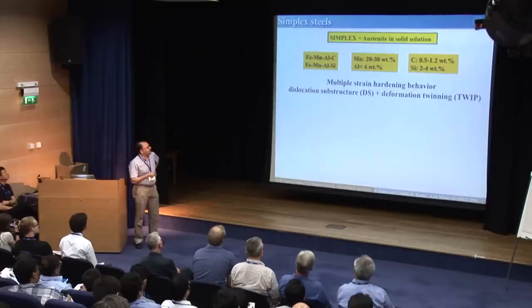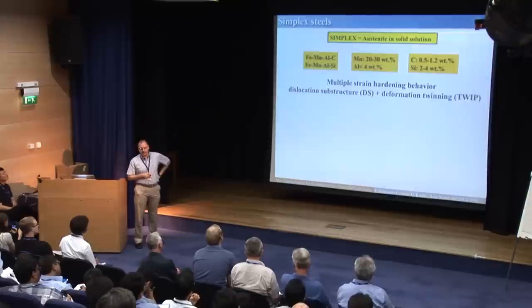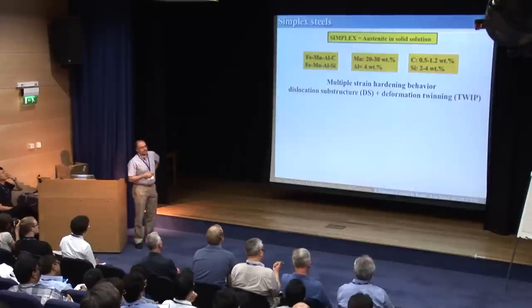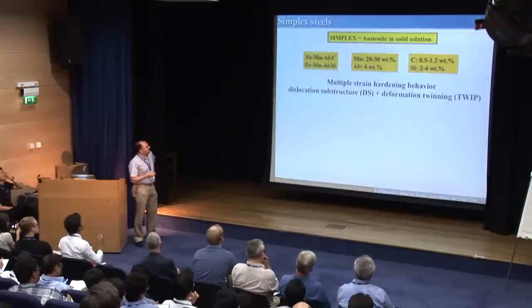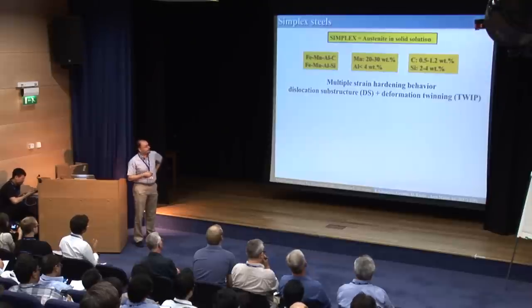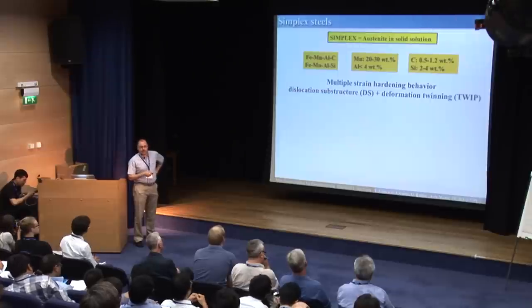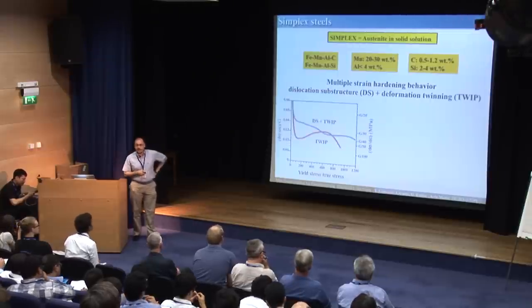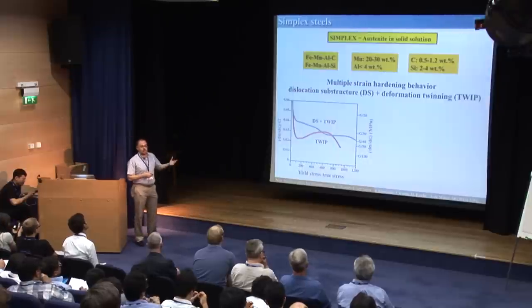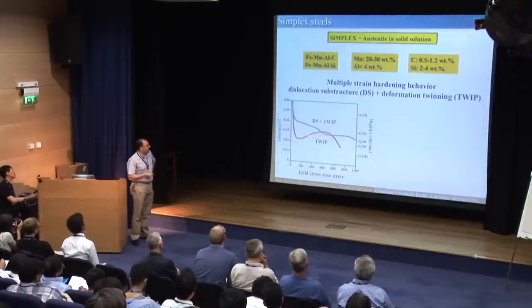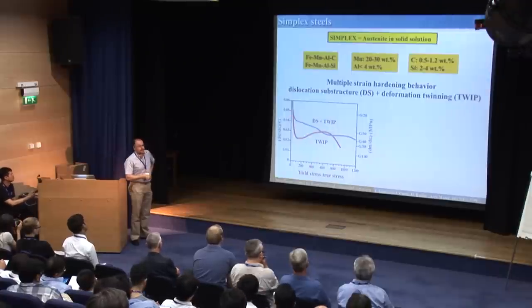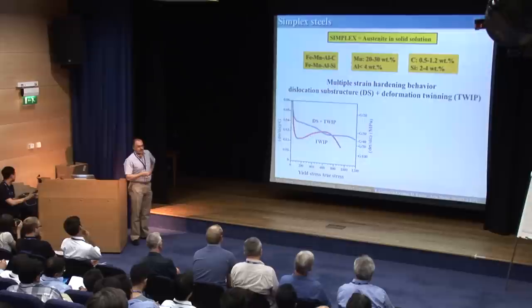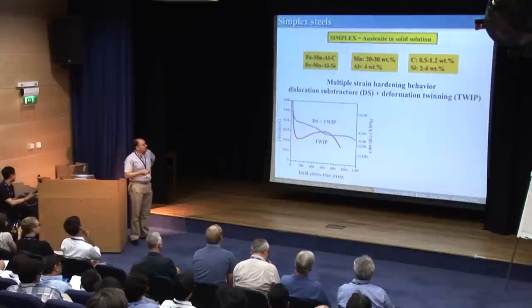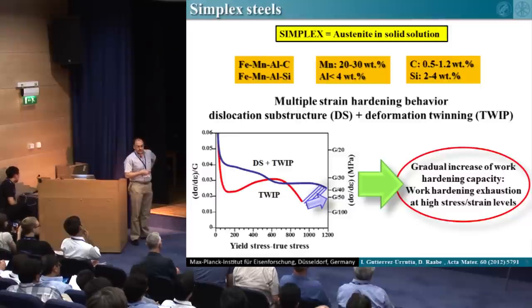And here, due to the alloying, the reason behind the outstanding strain hardening capacity is what we call a multiple strain hardening behavior, which is basically a two-stage hardening behavior. The first one is related to dislocation substructure hardening, and the other one is deformation twinning. So what we do in these alloys, instead of promoting twinning from the beginning, like what happens in the so-called TWIP steels, the ternary system, where the strain hardening increases at the early stages of deformation, is plotted here, leading to the classical Hollomon strain hardening. This is well known. Here, what we do is gradually increase the strain hardening.